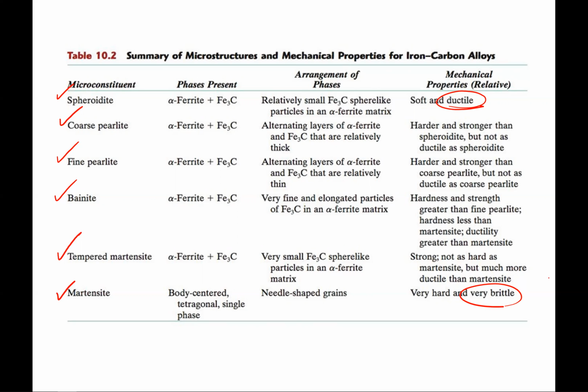Notice, though, the phase diagram tells us that ferrite and cementite is what we need in the final structure. So all of these structures here contain ferrite and cementite. This is what we expect from the phase diagram. The difference is that the kinetics are kicking in and saying something about how the cementite and ferrite look in terms of, are they spheres, what is their spacing, are they layers, are they needles, and all of that is affecting our mechanical behavior. And martensite, we said, was a non-equilibrium structure, so that's why it doesn't show up in the phase diagram. We only got this because we froze the austenite structure in essentially as we dropped to room temperature. We don't have enough diffusion to actually move carbon around to form the ferrite and cementite. So instead, because of all the strain, the system just distorts into a body-centered tetragonal structure rather than the original face-centered structure of the austenite.